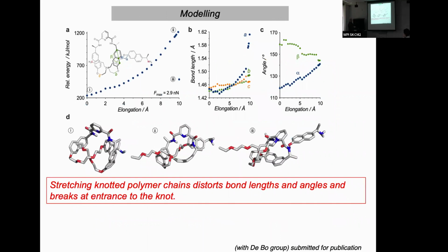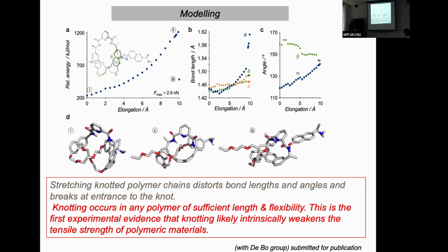So this is theoretical modeling of this actual structure, and we can see exactly what is happening. Stretching of this knotted polymer chain distorts the bond lengths and angles, and it breaks at the entry to the knot. So as knotting occurs, of course, in any polymer of sufficient length and flexibility, this is the first experimental evidence that knotting likely just intrinsically weakens the tensile strength of polymeric materials. So we're very excited about the possibilities that being able to make knots will give us for analyzing the behavior of knots in different processes.